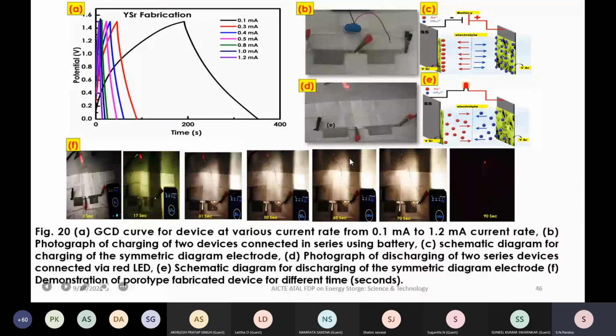So we have attached the red LED, and one can see the photograph after 3 seconds, after 17 seconds, after 31 seconds, after 50 seconds, after 60 seconds, and after 70 seconds. Even after 90 seconds, one can see here that the LED is glowing. So that is a very interesting result, that we made a device, and this device is a working one.